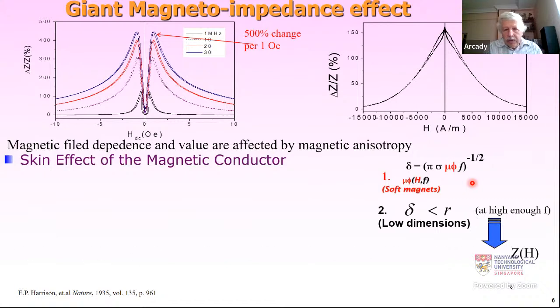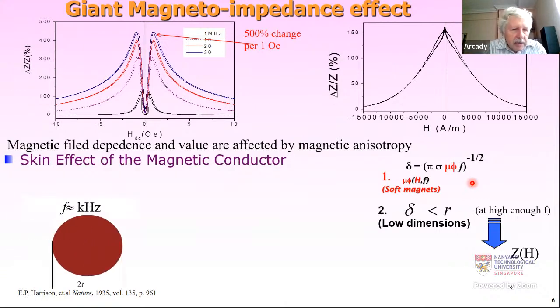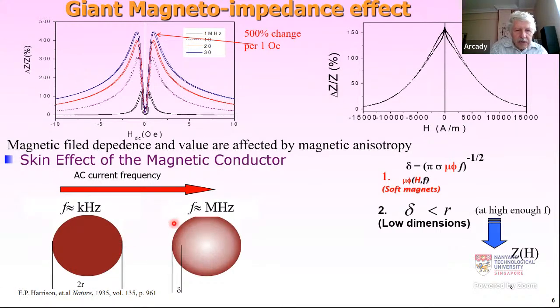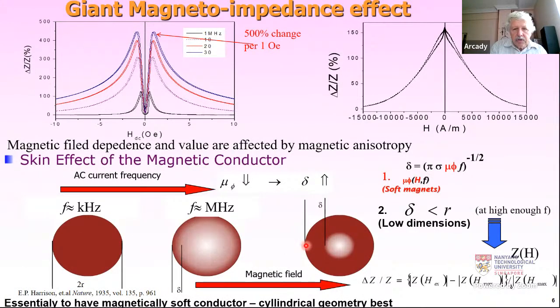Low dimensions are quite important because in this case, the skin penetration depth should be below the dimensions of the materials. Therefore, thin magnetic wires are important. And the origin of this effect could be understood from this picture. If you flow the current through your sample, this is the cross section of your sample, the current flows through the whole sample. Then if you increase the current frequency, the penetration depth is shown here, so the skin effect becomes relevant. And now if you apply a magnetic field, you have a change of penetration depth because of the dependence of penetration depth on magnetic field through the magnetic permeability.